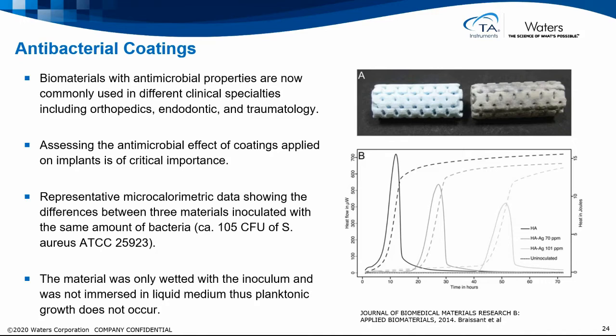So tests were made by doping it with an antibacterial molecule, and in this case it was silver. We can see in the graph here, the first solid grayish line is the hydroxyapatite alone inoculated with bacteria, and then the two coming ones have also been doped with silver. So we can see with silver we actually kill some of the bacteria, so it takes a longer time for the bacteria to grow to be able to form these biofilms. There was also a completely uninoculated sample, and we see that as a straight line at the bottom because there is no detection of bacteria. There is no growth of bacteria in that.